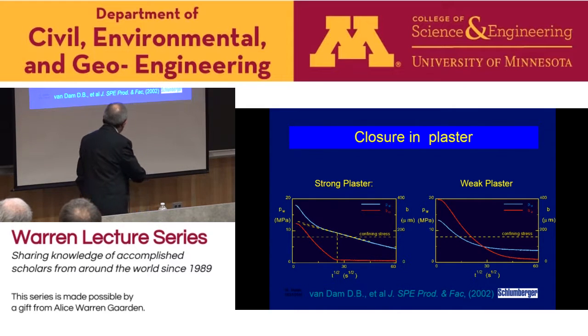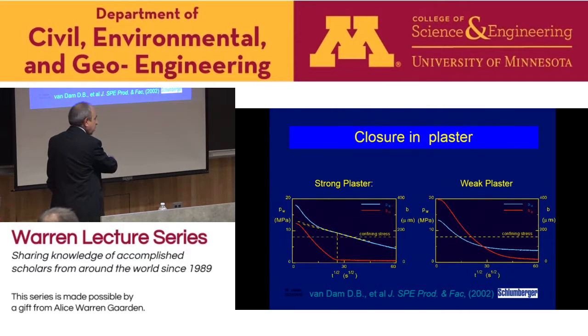In the case of the strong rock, the red line shows the fracture closure, the width of the fracture closure, which follows this pattern here. Someone can assume that the fracture has closed here. And if we take the pressure for this value here, we can see that the pressure is quite close to the confining stress, to the closure stress. So in that case, it will work quite well.